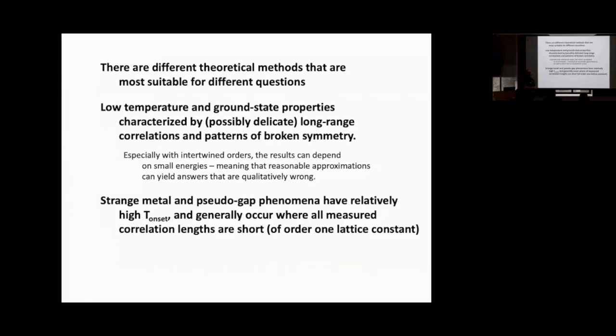Moreover, it's an empirical fact that in most of this regime, the correlation lengths of at least any orders that we can measure are quite short. So the physics is likely more local, and approximate treatments that manage to get the big energies in the local physics right can be extremely powerful.